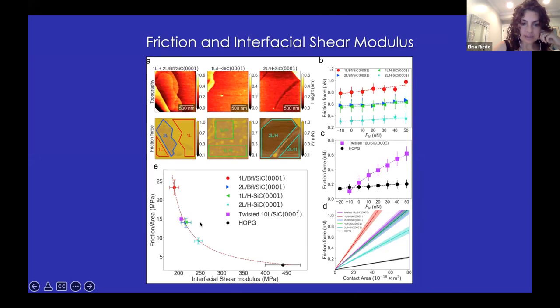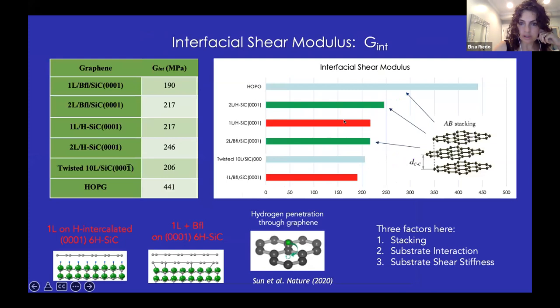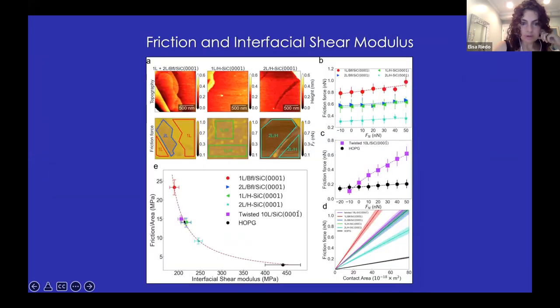Interestingly, what you can see here is that, for example, for the two materials that have the two layer and one layer structure, these two materials, by coincidence, have a very similar shear modulus. Well, they also have a very similar friction per unit area. So it really looks like the interfacial shear modulus is an extremely important parameter to control nanoscale friction.